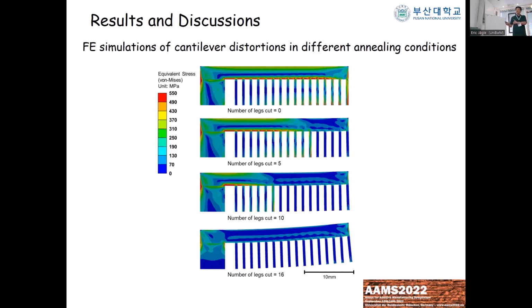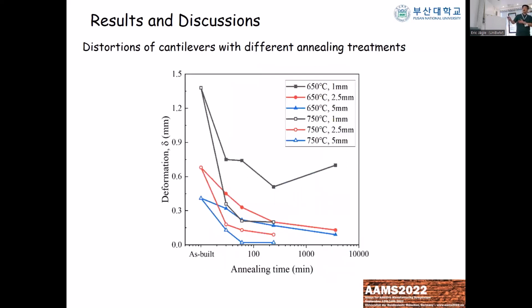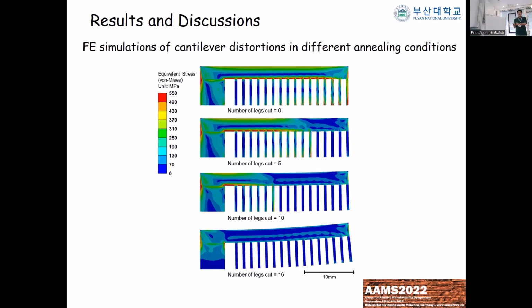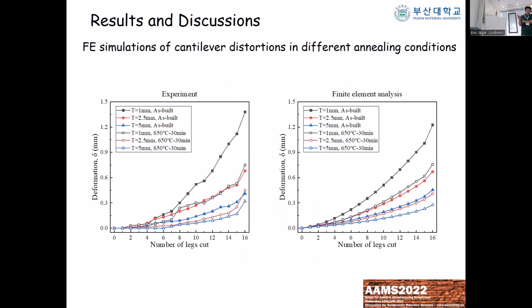Anyway, our model works like this, basically. It first calculates the original residual stress while we are depositing, and then it looks all the same actually, but with different amounts of stress depending on the annealing condition. But then when we cut, as in the experiment, it shows the distortion. And when we compare it and calibrate the model parameters to figure out how the simulation model can show the amount of deformation that is shown by the experiment, then we have the calibrated model. So with many experimental parameters, we could successfully obtain the fitted parameters.